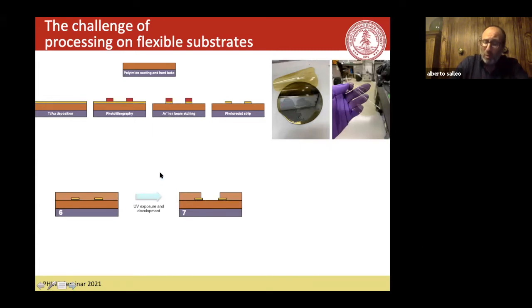But in the end, this was never perfect. You can see it here, it's still curled a bit. And so the idea is, well, if you put something on top of it that will curl the other way, it will keep it sort of under mechanical equilibrium. So we put another polymer on top of it. But now you have a polymer on top of it. You want to be able to access the region between the two electrodes to put your sensing polymer in between, so you can measure the conductance between the two electrodes. So you have to do what is called opening a window or cutting a window.